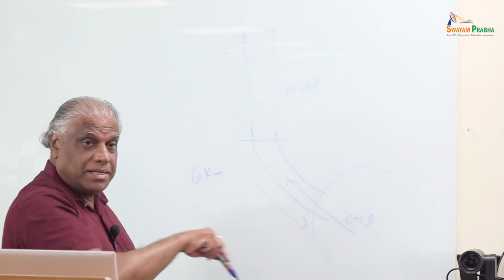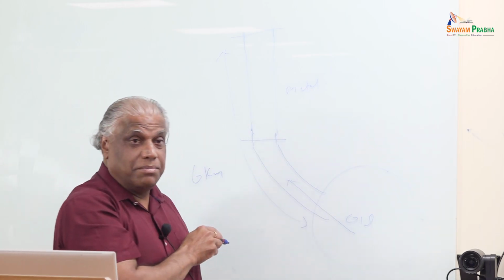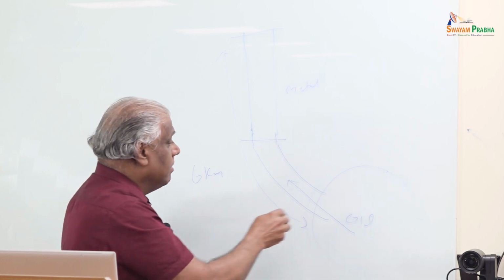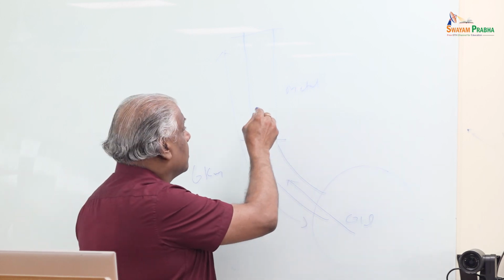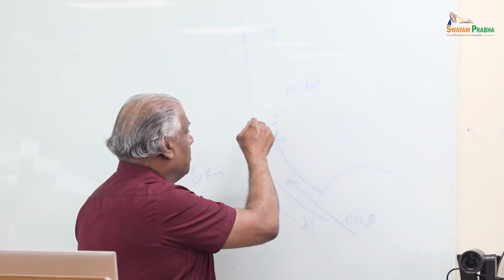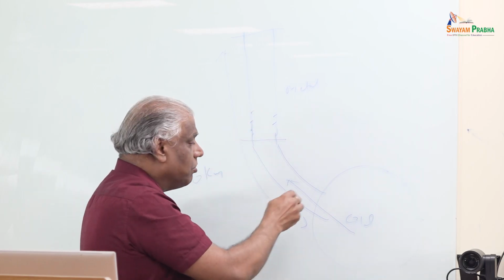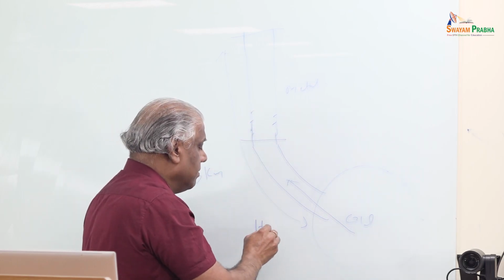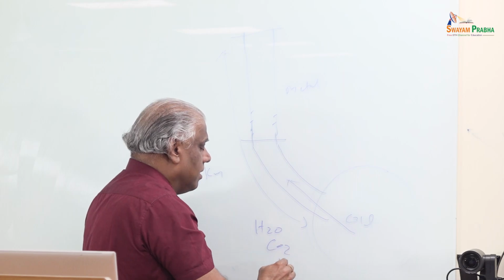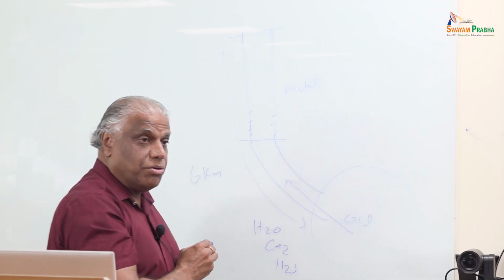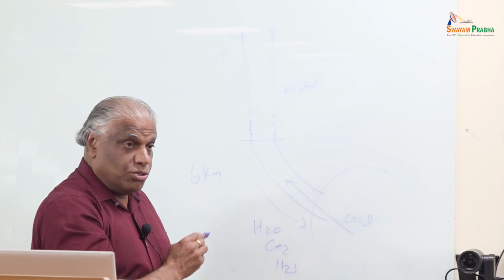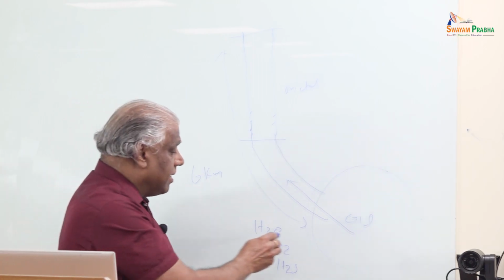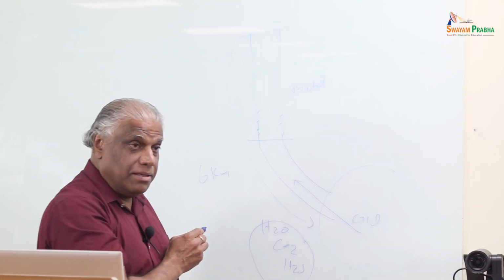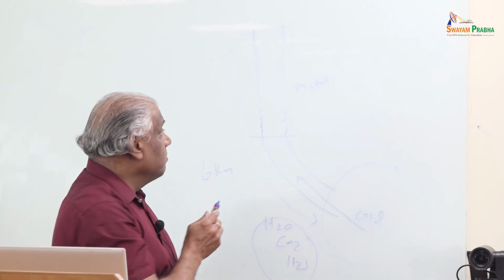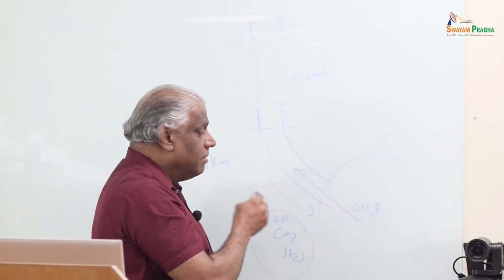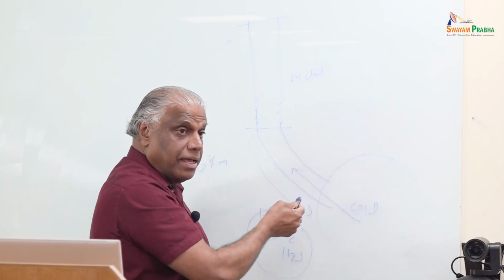So 6 kilometers they drill into this oil reservoir. Oil is coming out, and when the oil is coming out, it is in contact with this metallic tubing here, and this oil containing water as well, with the CO2 and H2S, and that is causing the corrosion problem. So that means that there is not much oxygen here in this case. Actually, the oxygen is coming from, sometimes what will happen is this reservoir.